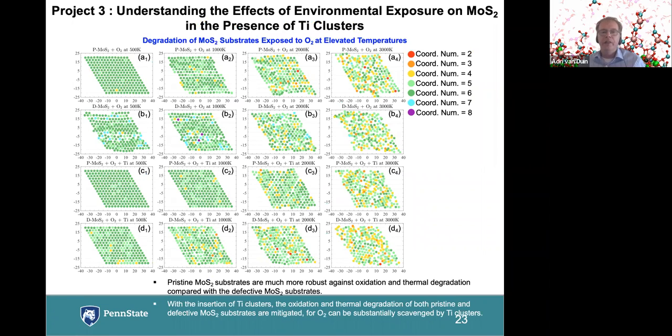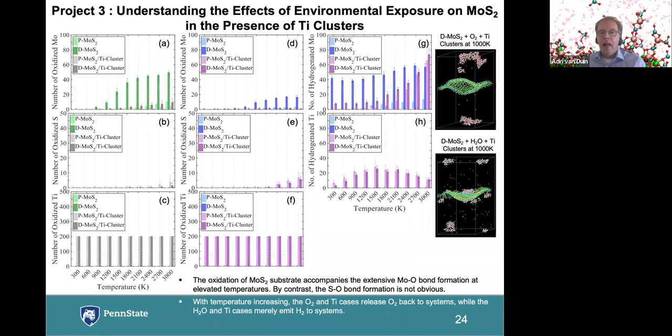We can express this in various ways and forms, and this is clearly a rich source of data. There are also data science games you can play with these types of plots, but you can essentially see where the localized damage is and how the damage then propagates into more substantial structural damage. In this particular case, we use the coordination number as a tool to gauge the damage, but there are clearly other ways to do that as well. This is actually pretty fascinating. Here are some snapshots on the right of what we actually see, and also how the titanium organizes itself.